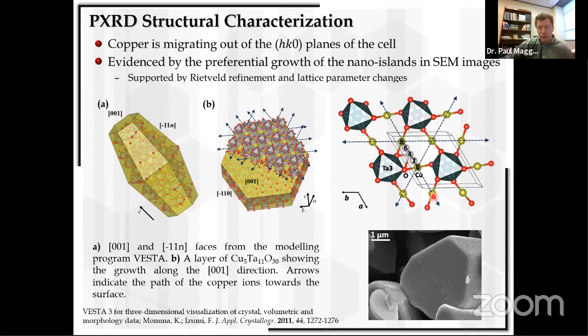And there are diffusion paths in all three crystallographic directions, or I should say within that plane, for copper to reach the surface and to be oxidized. Okay, and so even at 250, at 350, there's a high mobility of copper 1+. And in the presence of air, of course, copper 1+ will oxidize to copper 2+. Okay. So this is what's happening at the surface. As we heat it up, that copper is being driven out, and copper 1+ is being oxidized to copper 2. And that, in fact, is what's making it a p-type semiconductor.